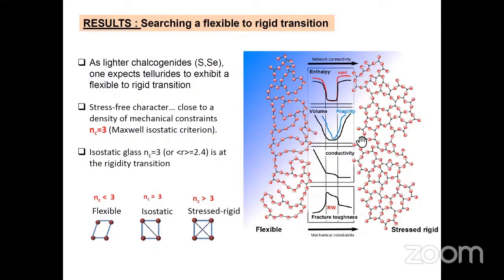And as you go through this increase, you will hit a rigidity transition, which is satisfied as the number of mechanical constraints matches 3, which is the number of degrees of freedom per atom in 3 dimensions, and which corresponds to a very well-known criterion in trusses or bridges, known as the Maxwell criterion or Maxwell isostatic criterion. In those networks, it happens at a mean coordination number of 2.4, the average coordination number.